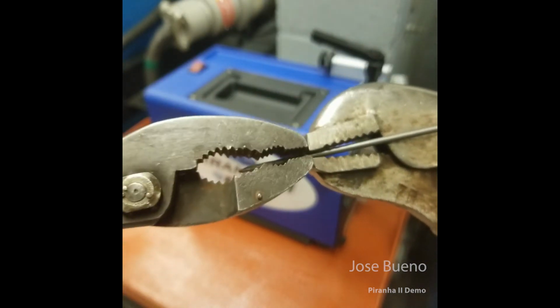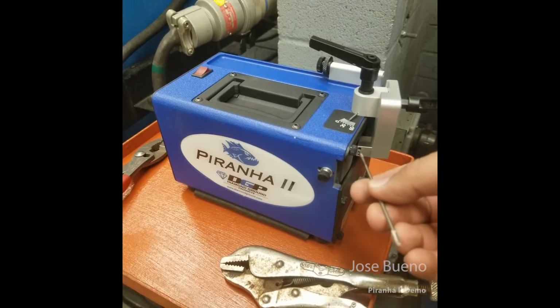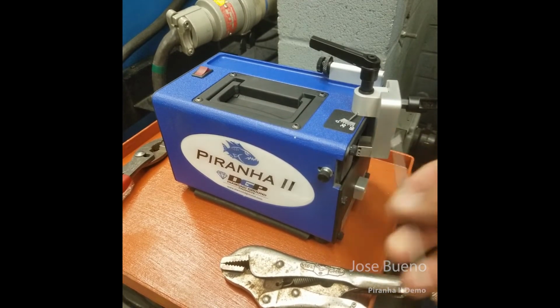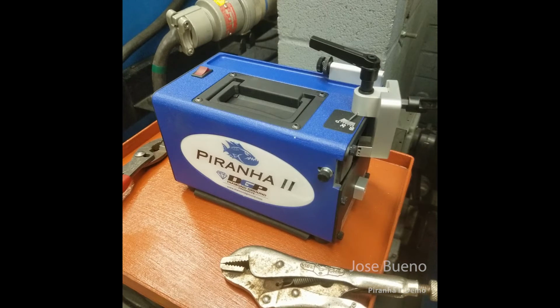There's one problem with that though. When snapping pieces off of our tungsten electrode, that can introduce stress fractures into our tungsten once we're done snapping the pieces off. And that'll later lead to further contamination and more tungsten migration, which is also called tungsten spitting, and we don't want that to be in our welds. So the Piranha 2 has some other stuff incorporated into it that can alleviate all of that.